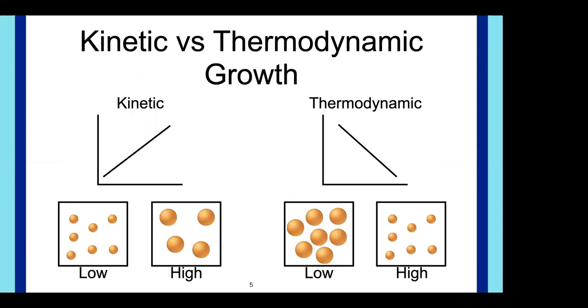Looking at the different kinds of growth realms that you could have, on the left, we have the kinetic growth system that was accessed in the Sorensen paper, which is a short time scale, quick reaction growth of these assemblies. At lower temperatures, you have more nucleation sites, so you end up with smaller assemblies formed. At higher temperatures, less nucleation sites, so the monomer units will build into larger assemblies.